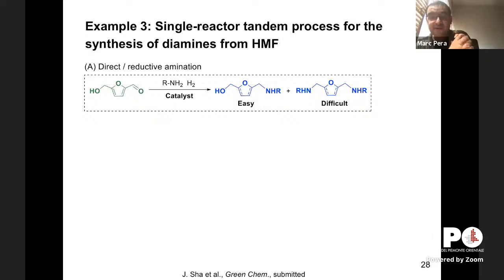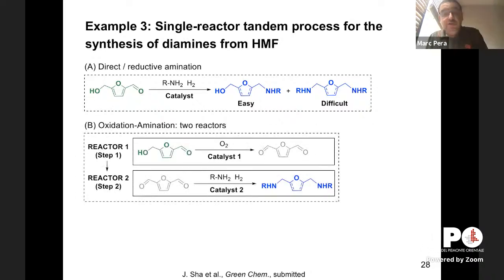The examples I showed so far concern the development of a single reactor process by combining an acid-basic center with a redox center. We can do aldol condensation and amination, aldol condensation and hydrogenation. But we can also combine two redox centers to do more difficult things. And this is a very difficult thing. So let's take now, instead of furfural, HMF, which has an OH. This OH is extremely poorly reactive, very difficult to react. So essentially, if you want to do reductive amination, you will obtain this intermediate, but not the second one. Very difficult to find a catalyst that is able to tackle the two groups at the same time. Very, very difficult.